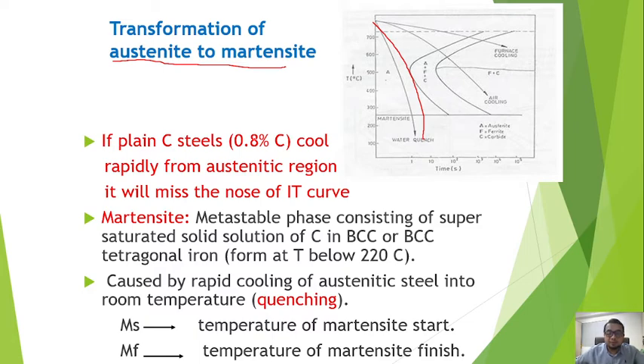So if plain carbon steel with 0.8% carbon is cooled rapidly from the austenitic region, it will miss the nose of the IT curve. This is the nose. Some people call it the nose of the IT curve. Looking here, okay, this is the nose. Right, here too it says it will miss the nose of the IT curve. So martensite is a metastable phase consisting of a supersaturated solid solution of carbon in BCC or BCT, body centered tetragonal, iron, formed at temperatures below 220 degrees C. BCC is body centered cubic. It is caused by rapid cooling of austenitic steel to room temperature, which is quenching.